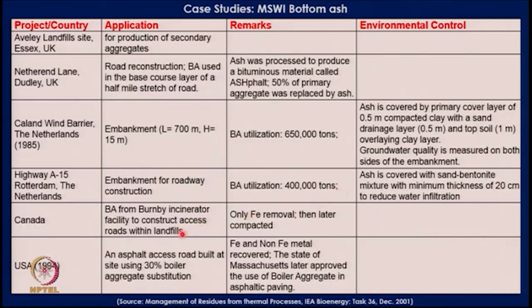In the other examples, bottom ash has been used within the landfill for construction of access roads, and also as a 30% substitute in aggregate for the asphalt access road in the US. So these are some examples of how MSW bottom ash after incineration has been used in different applications in roads and embankments. Well, that's all the testing that's been done so far. Data emanating from the world is that bottom ash in many cases can be utilized in geotechnical applications. So this is a front running area because you have 30% of the material which has to be taken care of. Landfills may become 1/3 their size, but they are not going to vanish.